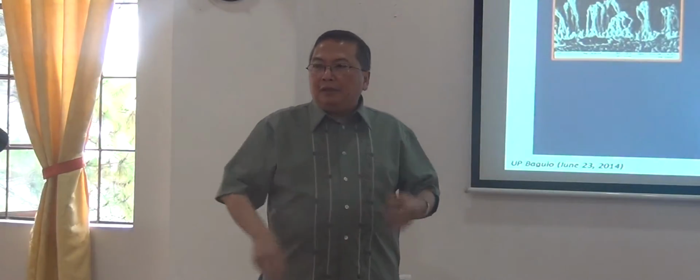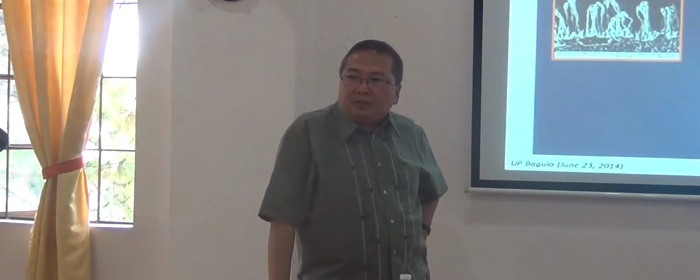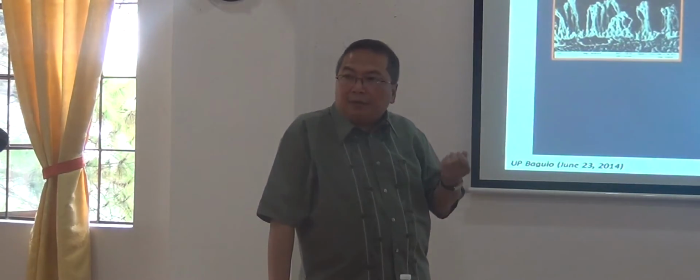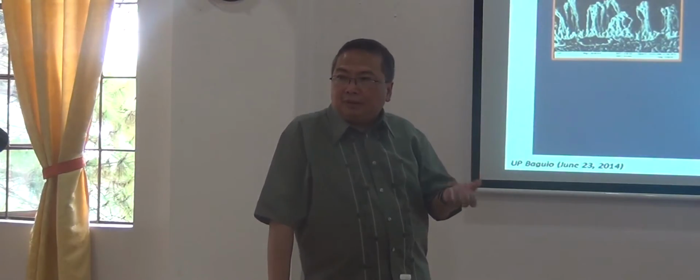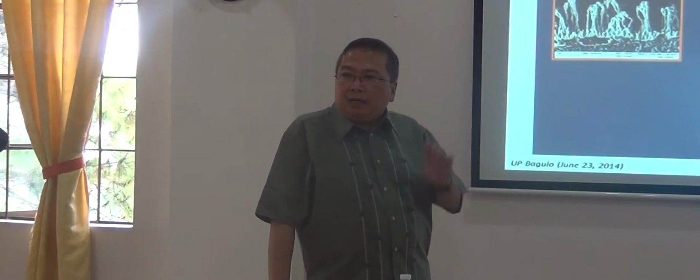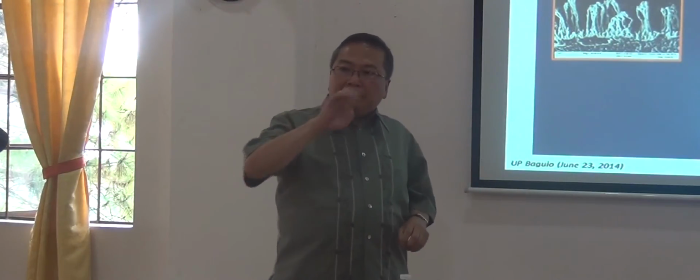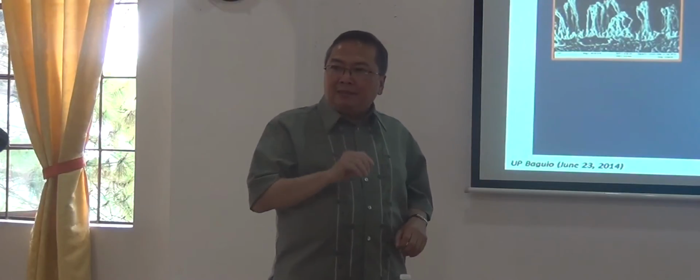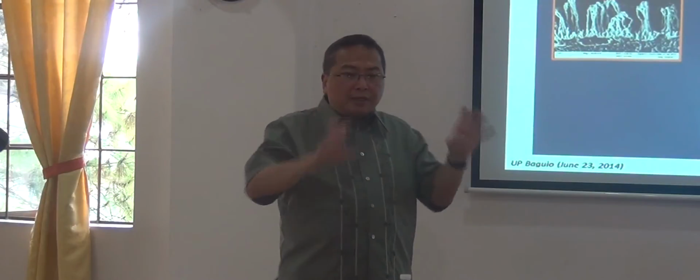What are the vacuum requirements? Pump down to about 10 to the minus 6 torr, but when it's actually pulsing, it's 10 to the minus 2, right? And then you need to buy valves, but what you need are pneumatic valves so that they are fast. It can't be solenoid. But those are standard.